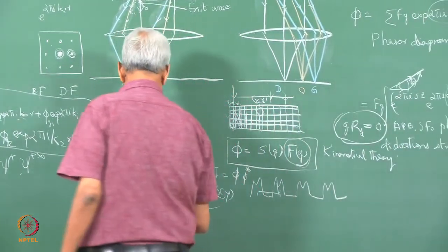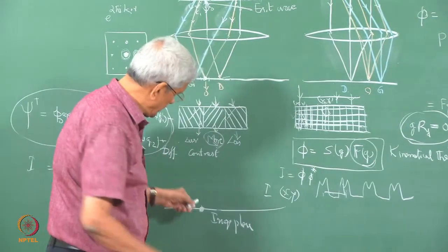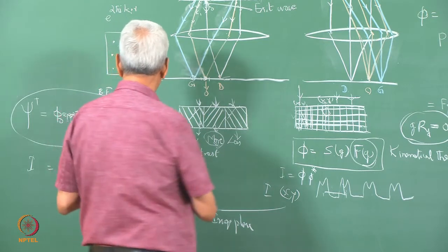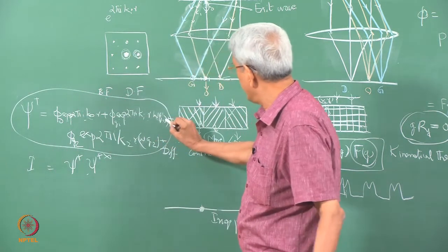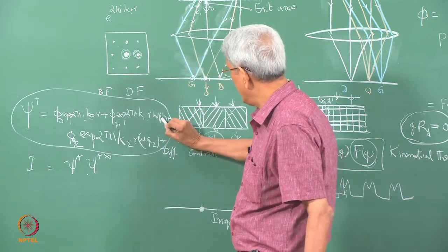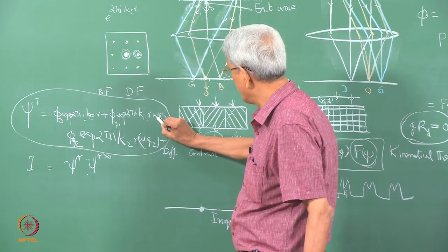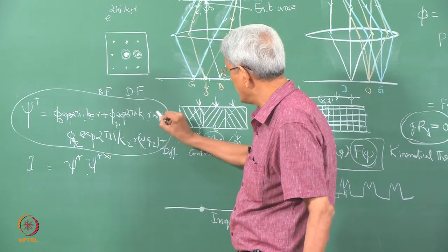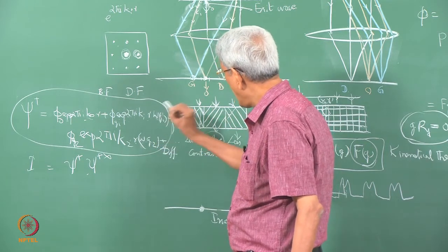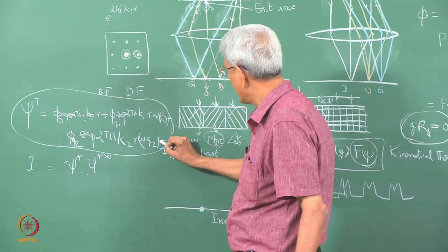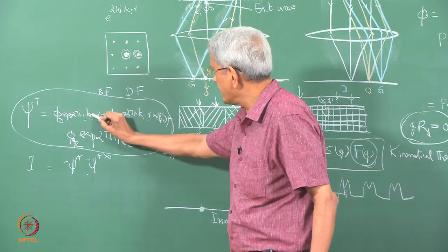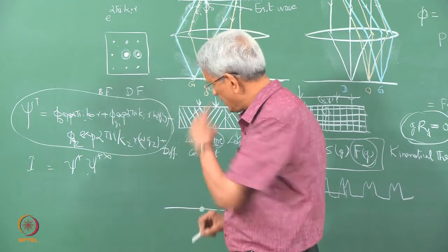in a high resolution image. So, to get a good contrast, what is essentially important is that these terms, the Wg1, this phase error which is being introduced by the lens, all of them should be of the same sign, so that the amplitudes add together.